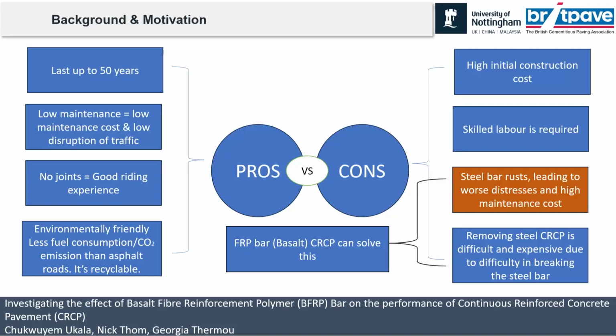at a time, we expect that if things go on, research has shown that steel tends to corrode. So if it rusts, some level of debonding can take place, probably at the point of the cracks. So if it cracks and there's some alkaline or acidic environment or carbon or what have you, we expect that this will rust. And if it's rusting, the bond loses strength, and we expect the crack spacing to increase, and therefore more rusting and more damage can happen to the CRCP.